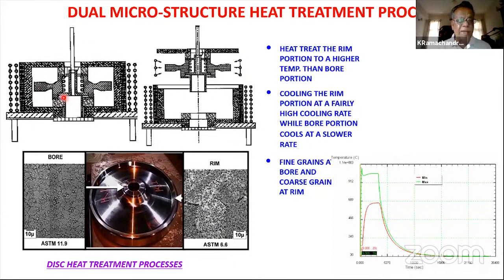into a heat treatment furnace or resistance heat treatment furnace and have fixtures to keep the temperature in the center of the disk, the bore of the disk, high, and on the outside you heat the rim. But once it is stabilized, you pull that thing out and you cool the rim very fast, keeping the temperature at the center of the disk the same. Don't allow it to cool down.